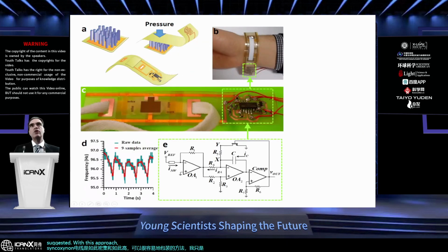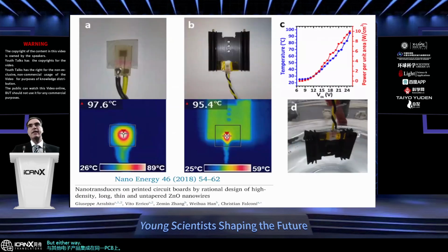With this approach, we could fabricate this bracelet that is entirely just the conventional flexible PCB, and we use it for monitoring the heart beat rate. We have other electronics integrated on the same PCB. But interestingly, to check that the quality of the device was very good, even with this very simple packaging, we just have the nanowires and package with another PCB on top.